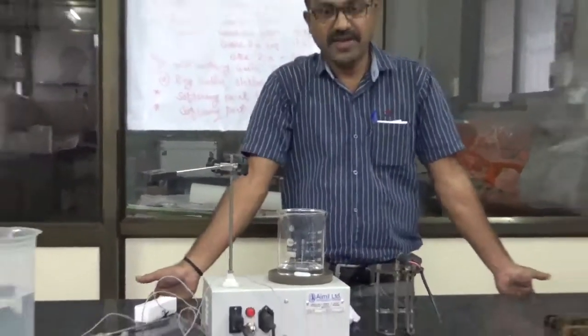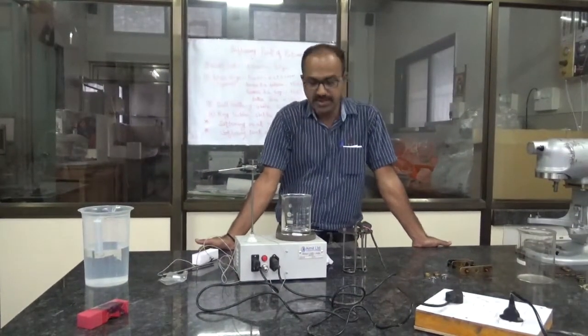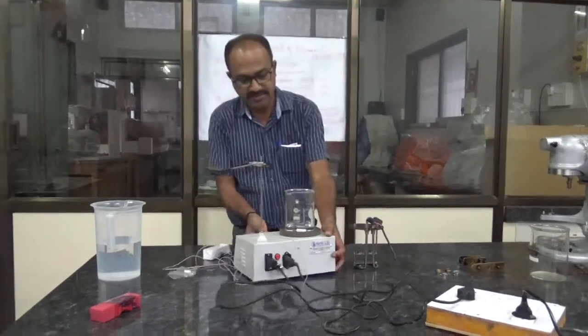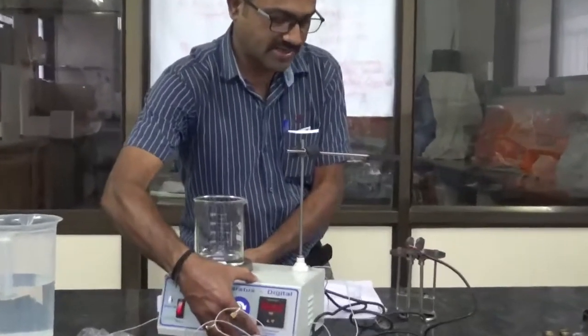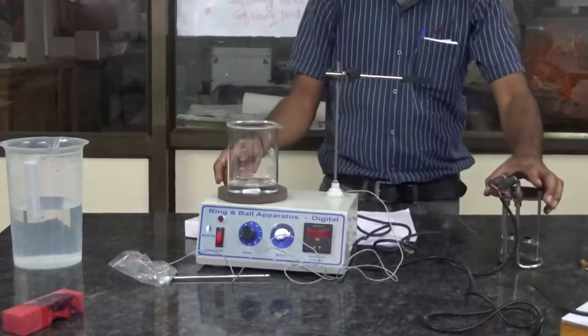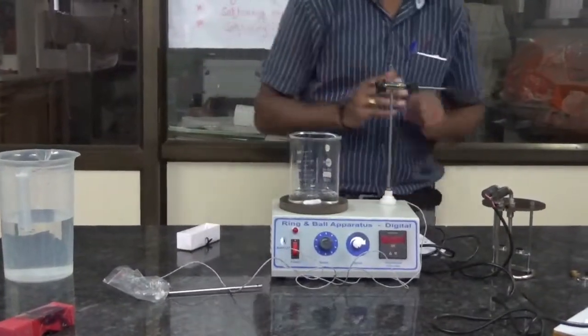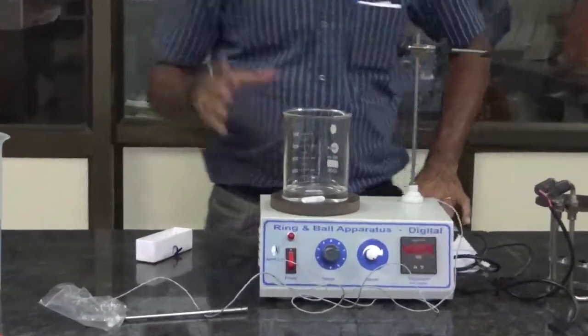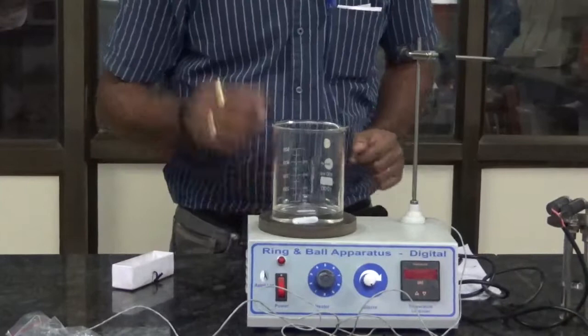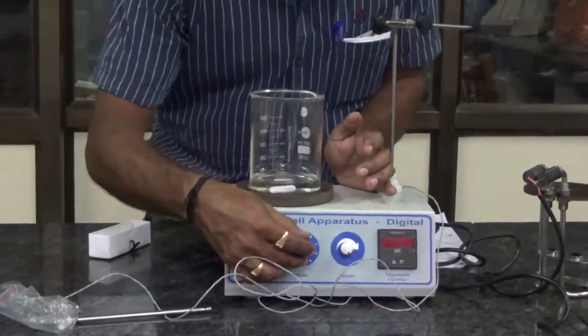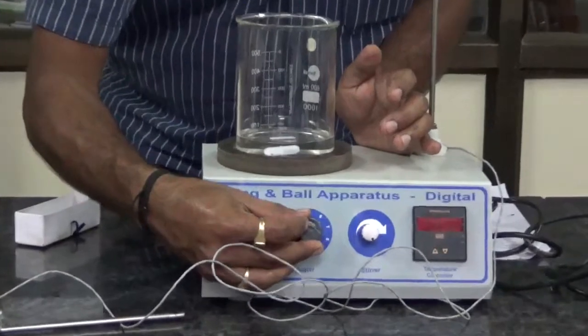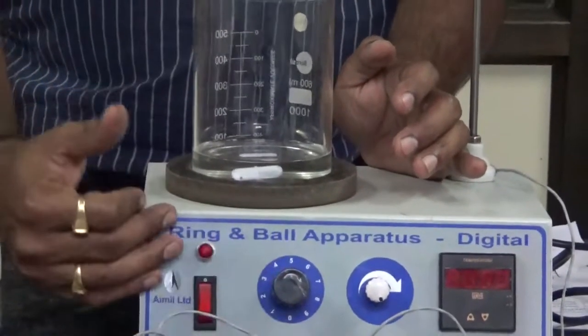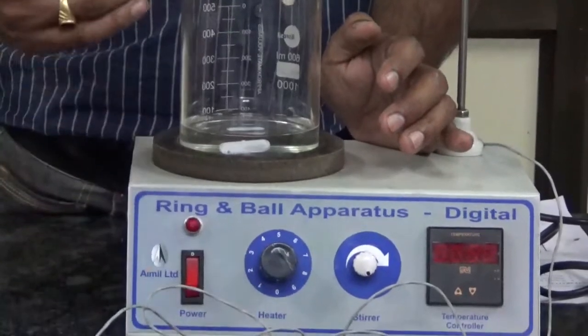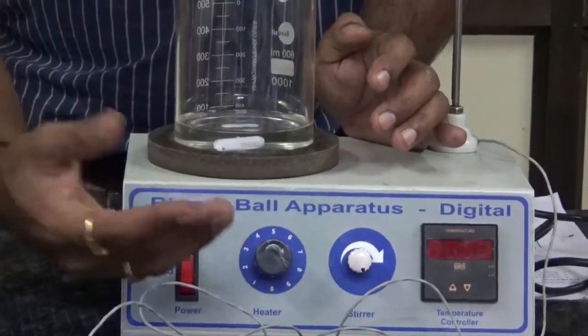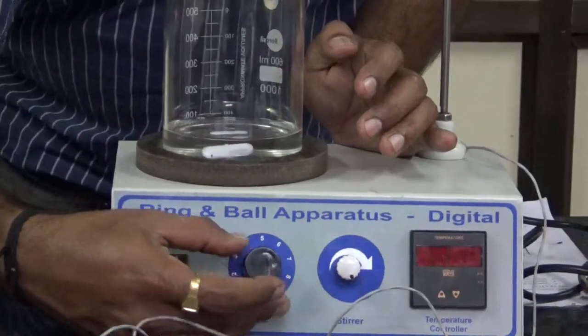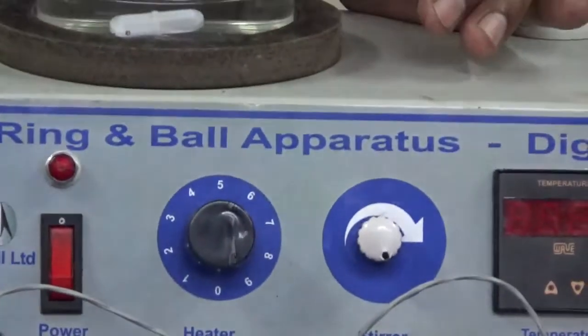Now, how can I find out the softening point of any bitumen? So this is my stage setup. This setup is called a ring and ball apparatus. Now, what are the different parts of this ring and ball apparatus? This is my thermostat where I can adjust my temperature. For finding out the softening point, we need to maintain a heating rate of 5 degrees per minute.